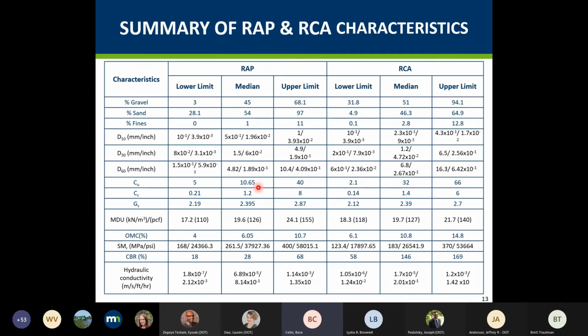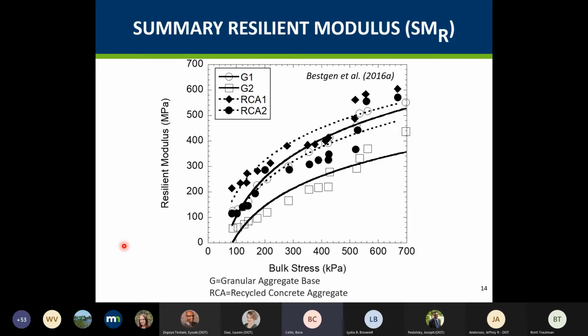And then, as you remember, if you look here, I listed the SMR, which means the summary resilient modulus value. When we correlate these index properties with the resilient modulus of the certain RAP and RCA materials that are used as base material, we use summary resilient modulus values, because pavement ME takes only one modulus input, if you choose to use that option as an input in your pavement design. So we use the summary resilient modulus value, which we call SMR. And what SMR means is that it is basically one single point of resilient modulus value for that particular material that we are interested in using as an input in pavement ME.